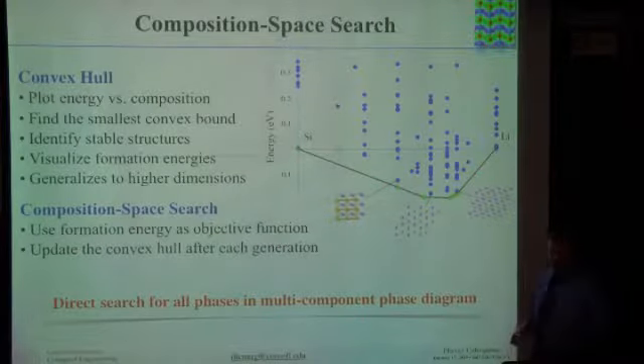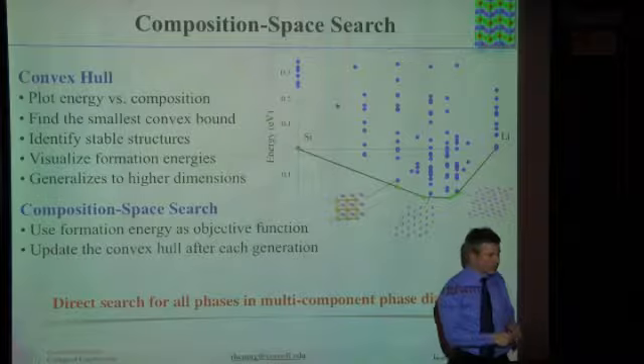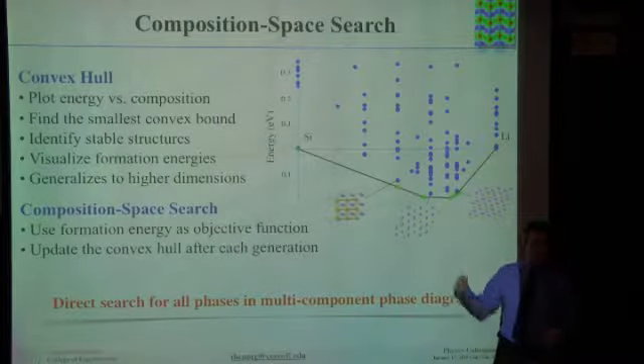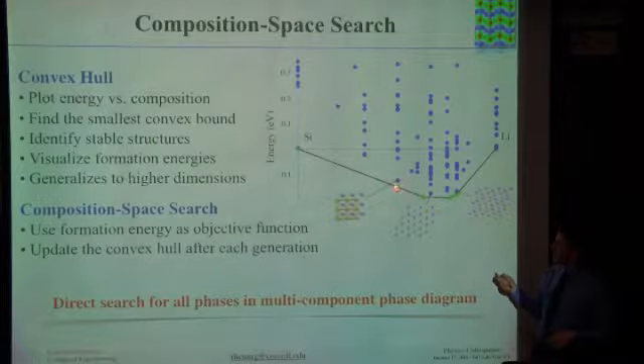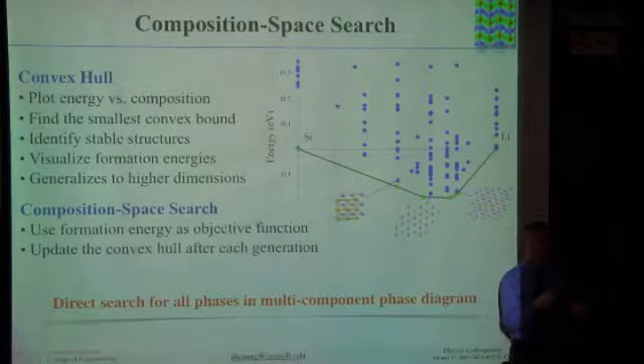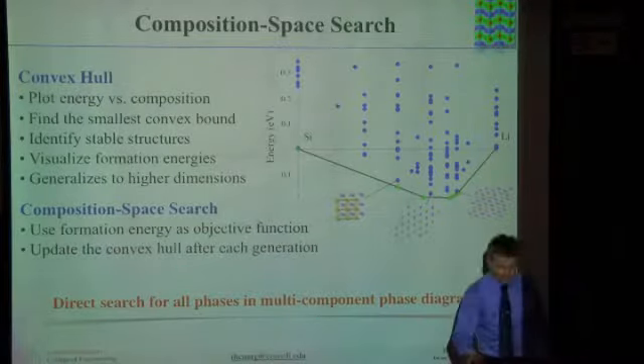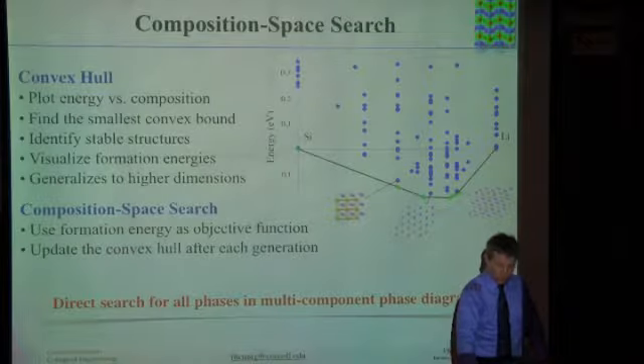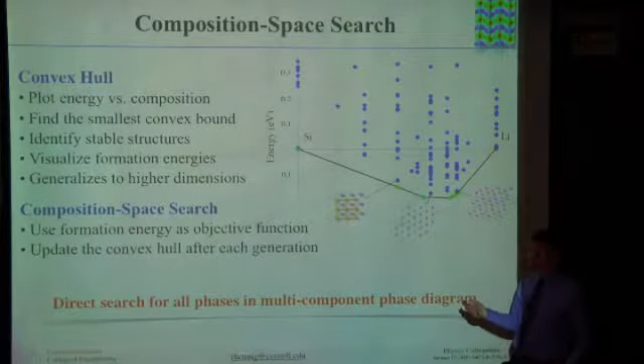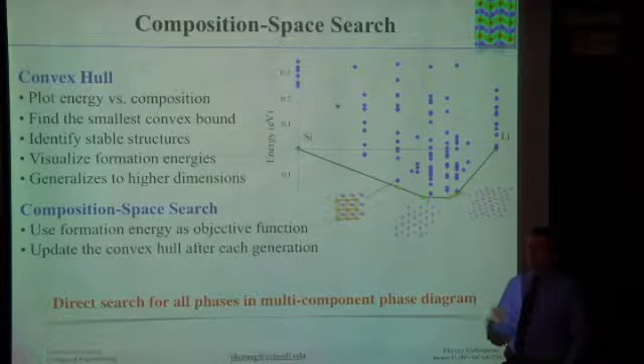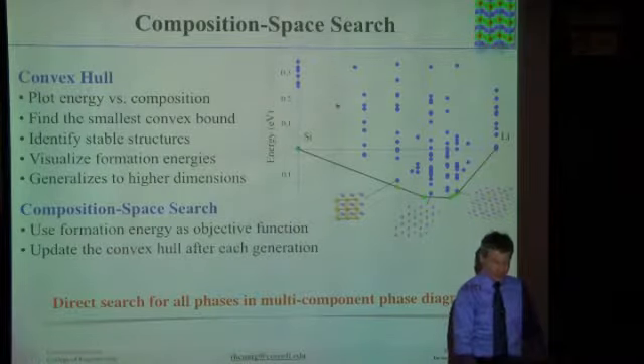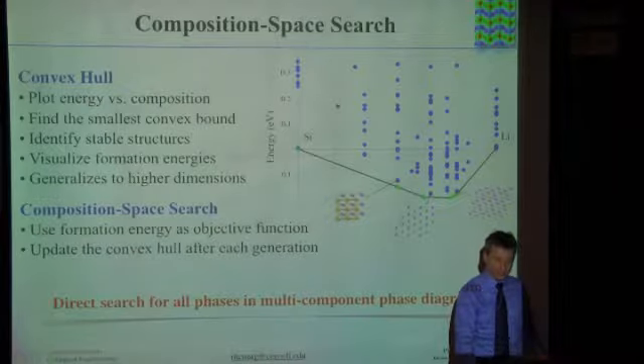The green points are the ones we're looking for. That allows us to illustrate where our structure search is by just plotting points like this, and it allows us immediately to identify how stable a structure is. On the convex hull, stable. The closer it is to the convex hull, the better it is as a candidate for the next generation of structures. Our algorithm works in arbitrary dimensions, so we can look at binary, ternary, quaternary, but we're running out of speed very quickly. We have never tried a quaternary because the DFT calculation would be getting terribly slow. It could be way too many structures.